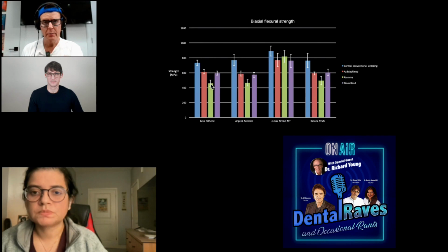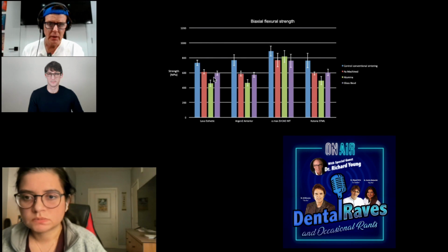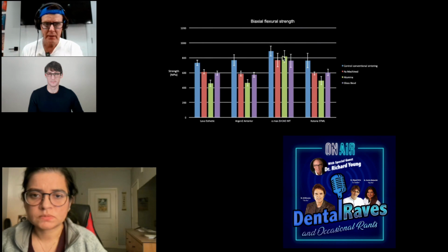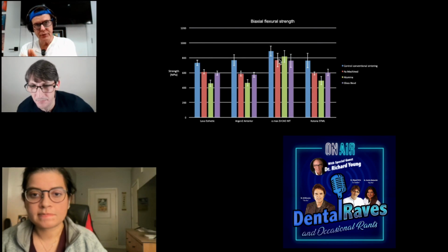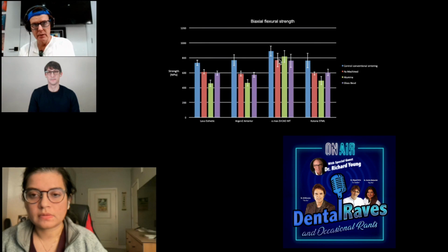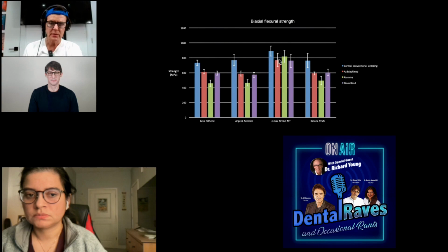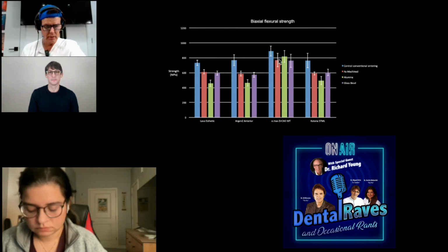So you want to know the percentage of yttria in your material. The other point, and we're also looking at these gradient materials, is that if you have a 4Y or a gradient material, in other words a little bit higher or lower yttria content, they still maintain their strength if they are sandblasted. So the materials to use today for single crowns are the most translucent, a 5Y, or a gradient material that has 5Y. For bridges, a 4Y, or a gradient material that has 3 or 4Y. You can ask in the questions which ones, and we'll give you some names of materials later. That basically, I believe, is really the message of this paper.